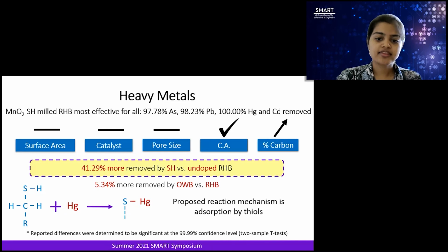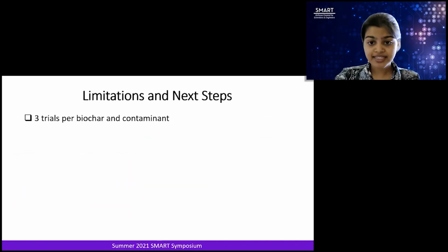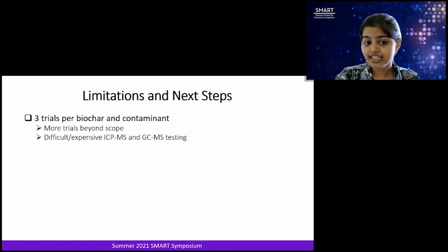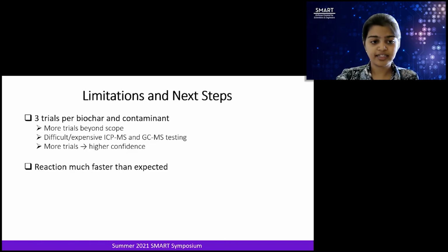Now, looking at the percent of heavy metals removed by thiol-doped biochar, we can conclude that the proposed reaction mechanism likely involves adsorption by thiols. This would be very similar to the previous reaction mechanism we had seen. Some limitations of my research are that I only conducted 3 trials per biochar and contaminant type. More trials were beyond the scope of my research due to difficult and expensive ICP-MS and GC-MS testing. However, more trials would have resulted in higher confidence.